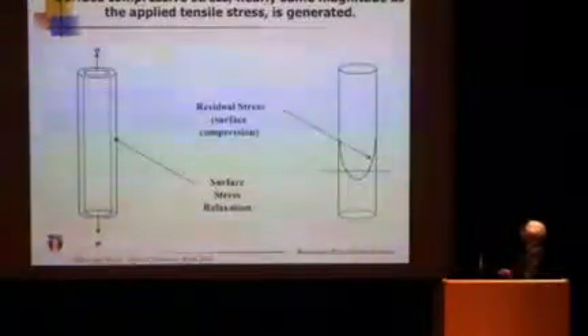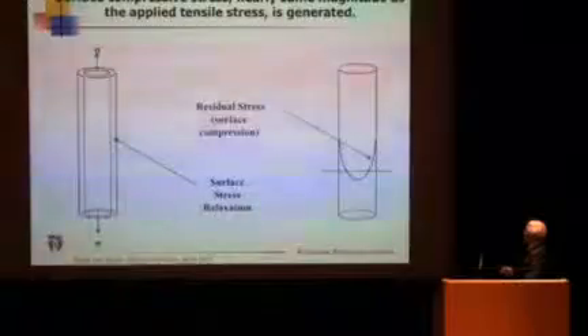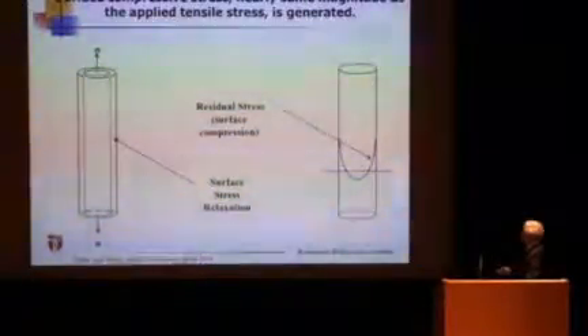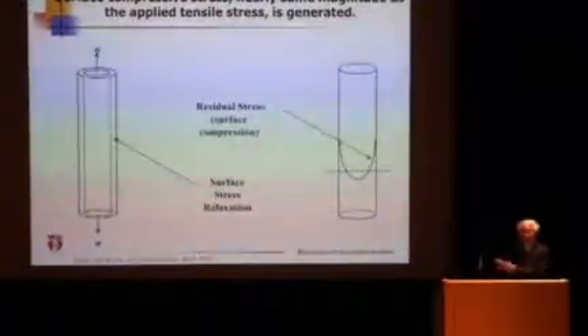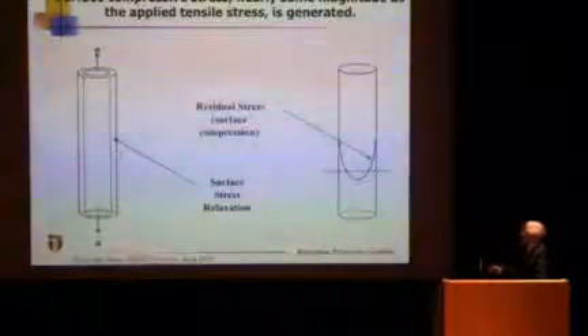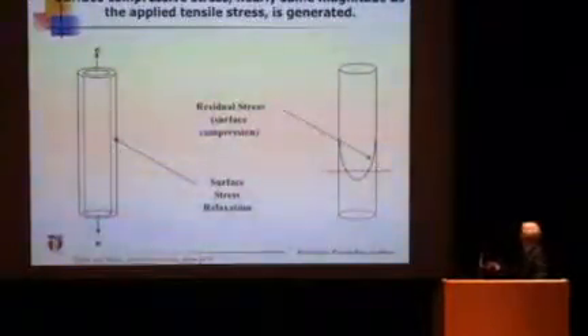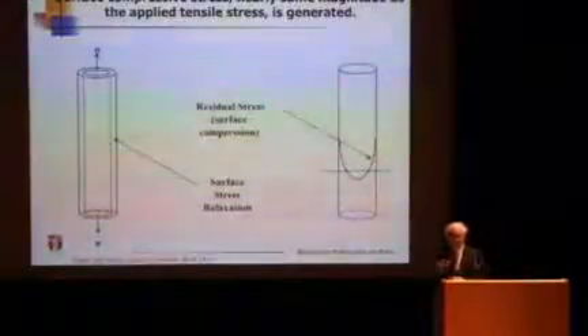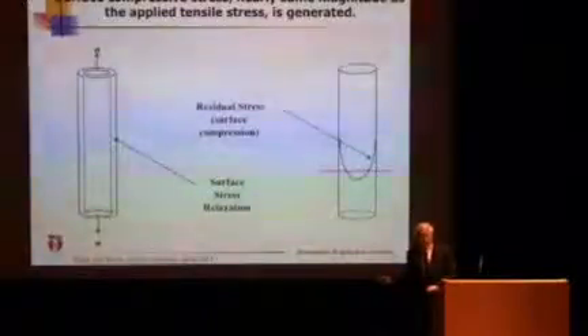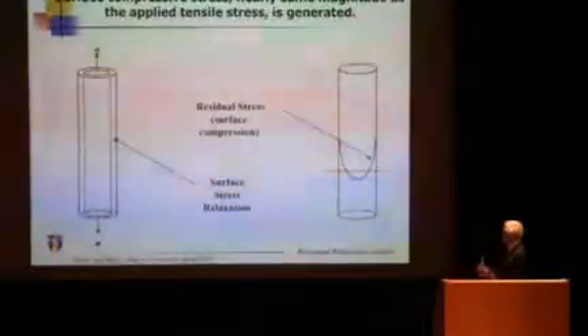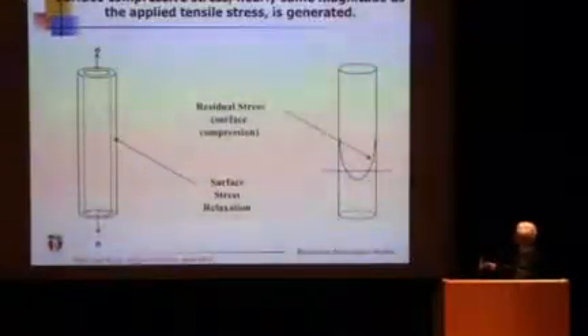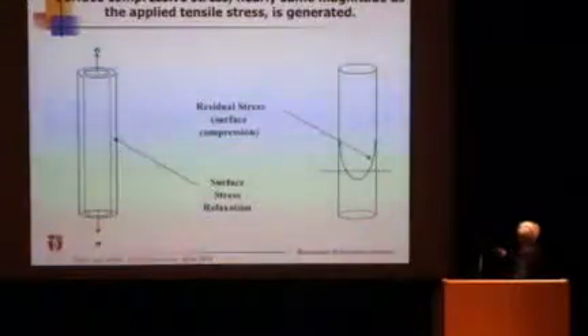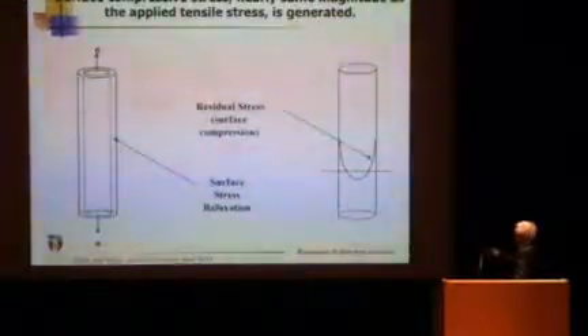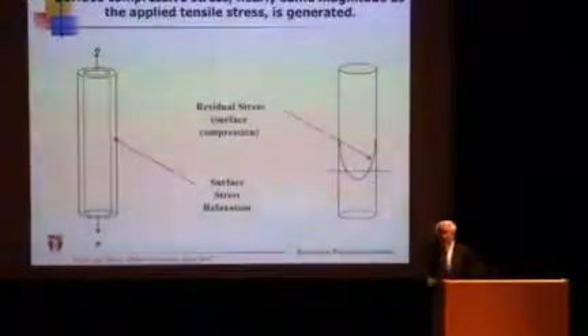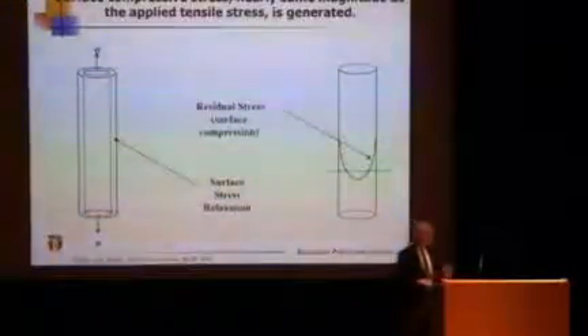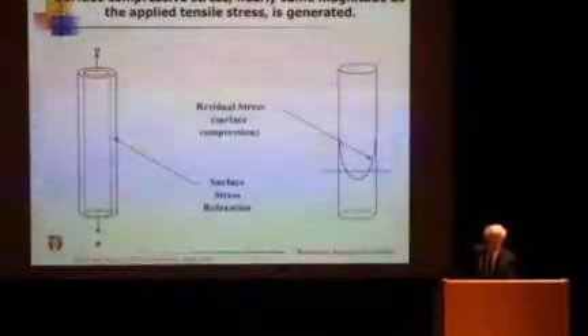Now first, how can we apply this observation to make glass stronger? You take a fiber and pull. This is a uniformly applied tensile stress. Of course, if you pull too much, it must break. So you do this under subcritical tensile stress. Maybe for optical fiber, you can apply 5 gigapascal. In this case, we apply 1 gigapascal, 2 gigapascal in air, at 200 degrees. And let go. Then the surface stress relaxation happens. That would translate into compression. This was tension, and you relax, let go, and you get compression. That surface compression formation is a practically useful way to make glass stronger. So I thought this can be used to make glass stronger.